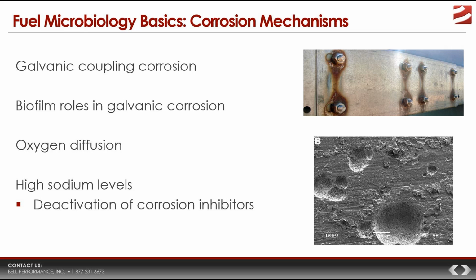What can happen is if you have layers or patches of biofilm on the tank surface, you get the creation of electropotential gradients between the covered parts and the uncovered parts. So you get a difference in the electrical potential between those two areas. That leads to galvanic corrosion and the creation of pinhole leaks like what you see in that electromicrograph picture there. Oxygen. The presence of oxygen also plays a key role in the development of corrosion damage. Many people don't realize that when you're comparing hydrocarbons, like diesel fuel, to water, oxygen's actually a lot more soluble in fuel than it is in water. Fuel can typically dissolve upwards of about 60 parts per million of oxygen, whereas water can dissolve about 8 parts per million.